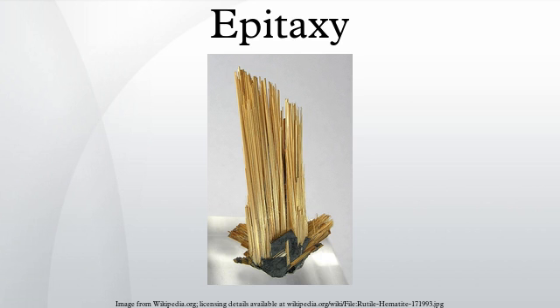Epitaxy is used in silicon-based manufacturing processes for bipolar junction transistors and modern complementary metal-oxide-semiconductors, but it is particularly important for compound semiconductors such as gallium arsenide. Manufacturing issues include control of the amount and uniformity of the deposition's resistivity and thickness, the cleanliness and purity of the surface and chamber atmosphere, the prevention of dopant diffusion from the highly doped substrate wafers to the new layers, imperfections of the growth process, and protecting the surfaces during manufacture and handling.